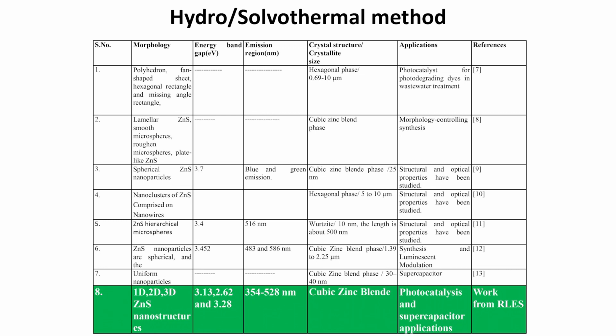The other method, the hydrosolvothermal method, by which we have grown different types of morphology, is the polyhedron, fan shaped, sheet, hexagonal, rectangle and missing angle rectangle, and the crystal structure is the hexagonal phase and the crystallite size is of the order of 0.69 to 10 micrometer, and the potential application is as a photocatalyst for the photodegradation of dyes in wastewater treatment.